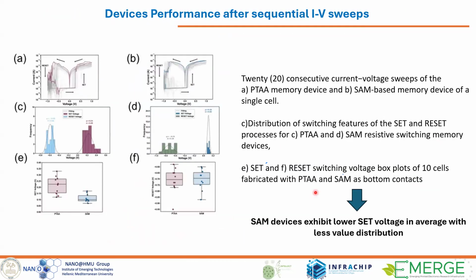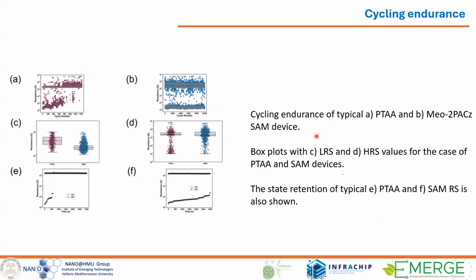So just very briefly, here are the data. On the left are the PTAA devices, on the right are the SAM-based devices and the comparison. And the result here is that SAM devices exhibit slightly lower set voltage, and also the distribution of set voltages was lower compared to PTAA. So this was an improvement. And also in terms of cycling endurance and stability tests, again, some devices were better than the reference PTAA device. So we gained both in terms of sustainability, but also a small improvement in terms of performance.